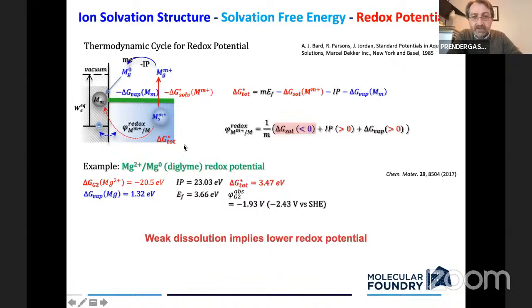One important thing to keep in mind, if we admit that there are multiple free energy minima, there is a way you can relate the redox potential to the solvation free energy. So the overall free energy of the conversion of, let's say, metal ions from their bulk forms in solid metals can read like this. Let's say you vaporize the solid, that's what this term is, then you ionize the solid atoms in the gas, and then you solvate them, and then this term here reflects the position of the potential, basically. And the only term here that really depends on the solvent is this middle one, the solvation free energy. The other ones are kind of isolated, either in the bulk or in vacuum.